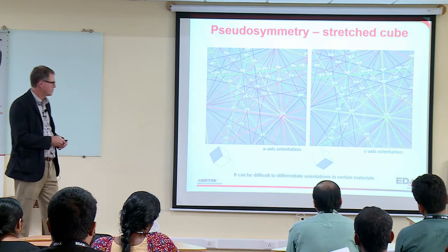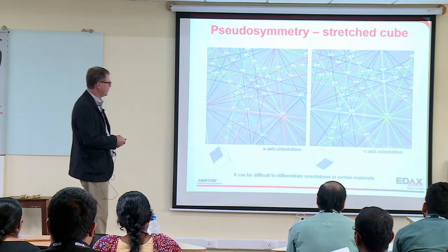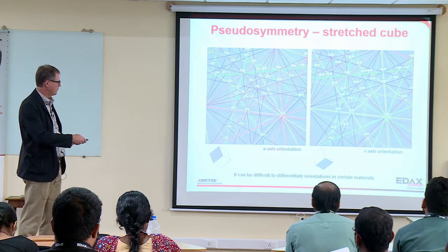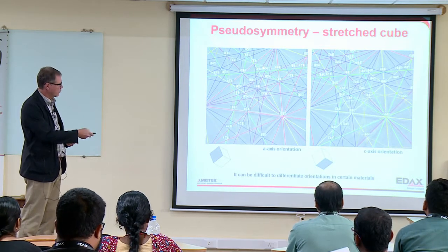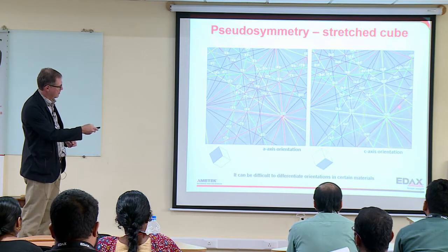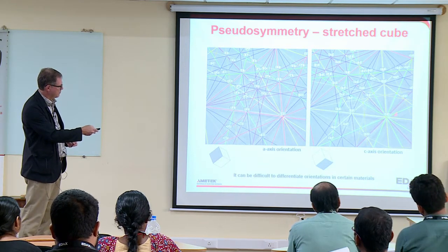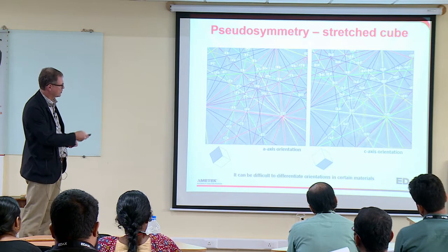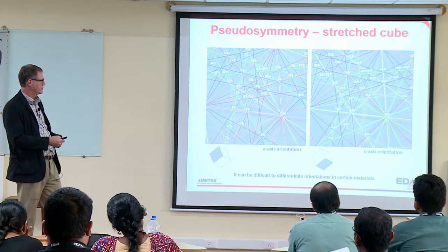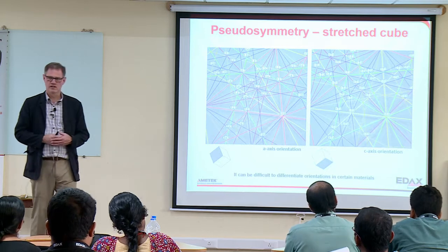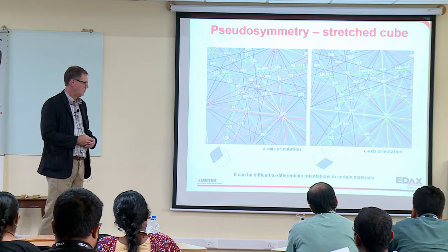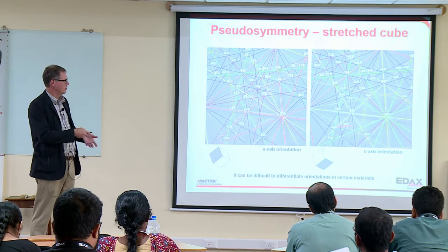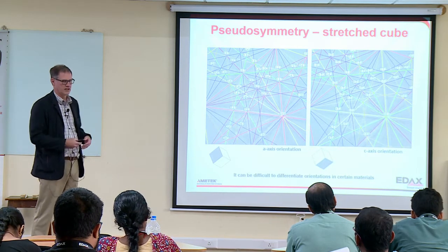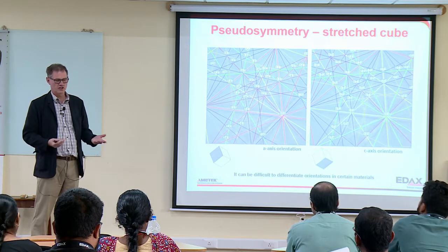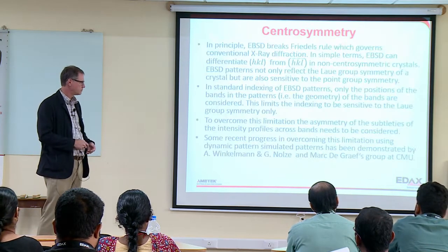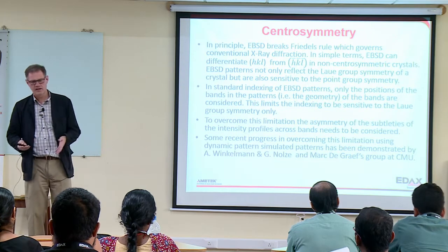But if you look at the patterns from that structure, you can see they're almost identical, even for these two different orientations. If you look really close, you can see this band here, the overlay doesn't match the pattern quite as well as this one, and they're shifted from each other. So in this one, there is a little bit of hope of differentiating these, but typically that would be a difficult sample to do. And so we call this pseudosymmetry. Usually what happens is we end up indexing this as if it were just cubic, which is a shame because then we've lost some information. But we're working on different techniques to try to improve this.